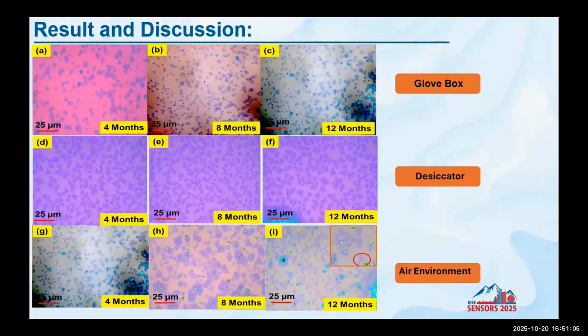But here I want to add a few points. In this work, I have highlighted the result only for these three environments. I have also studied a few other conditions, because that study is continuously going on, in different humid conditions, let's say 47% relative humidity, 75%, 87%, and under UV exposure. I have kept samples in these conditions and am continuously observing how the degradation rate becomes faster in different environments. That study is not concluded, so I didn't show it here.